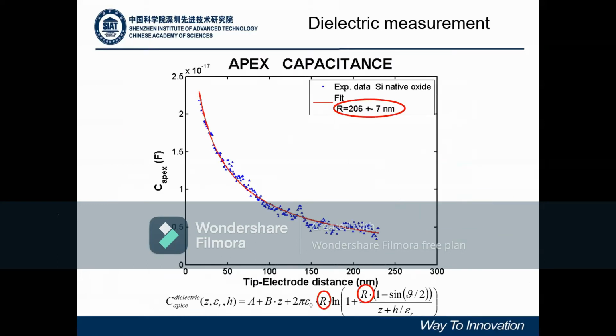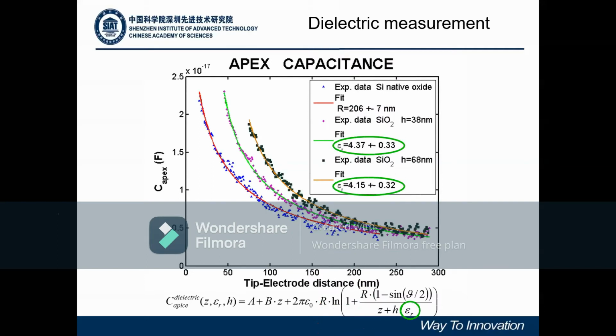And then measure the dielectric constant. So here is an example of this two-step measurement focused on the capacitance of the apex of the probe. The first step is used to measure the radius, in this case like 200 nanometers. And then the second run, you can see two different examples on silicon oxide with a thickness of 40 nanometers or 70 nanometers, where it's possible to fit and measure the dielectric constant around 4.37, 4.15, as expected for silicon oxide.